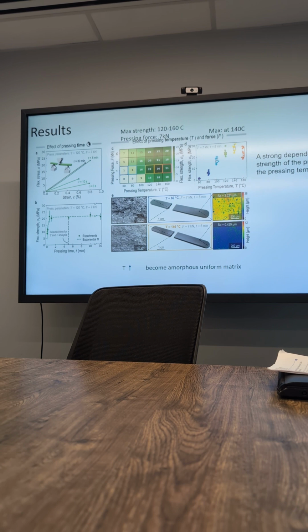And then of course after they get their material, they try to characterize it, try to know the basic mechanical properties of their material. So that's what they did. They try to add some pressing force at different temperatures. They try to know the relationship between the stress and the strain, try to get the modulus, and try to get the stress. So from this figure we can see when the temperature is from 120 to 160, they have the most amazing pressing force.